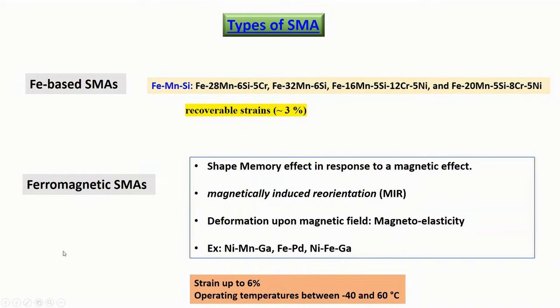Then amongst the iron-based SMAs, there are also ferromagnetic SMAs, which have this kind of shape changes and phase transformation due to the magnetic effect. Okay, so they have magnetically induced reorientation. So the kind of shape change, the kind of phase transformation that you have seen can be achieved just by changing the magnetic field itself. And the examples are of nickel, manganese, gallium based alloys and iron-Pd and nickel iron gallium based alloys. And this material has some strain of around 3 to 6%, and this is operating within the temperature limit of -40 to 60 degree centigrade.